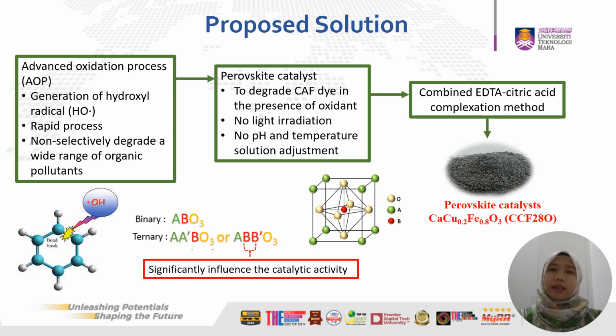So what are perovskite catalysts? Basically, perovskite catalysts are crystalline ceramics that belong to the group of mixed oxide with the general formula of ABO3. From the literature, it has been reported that the catalytic activity of the perovskite can be significantly influenced by the partial substitution of the transition metal into the B sites of the perovskite structure.